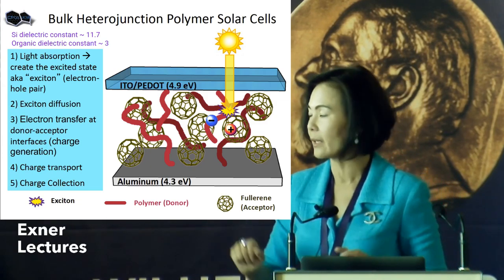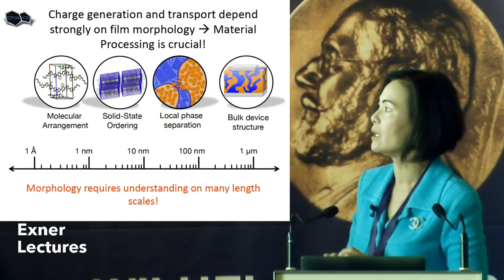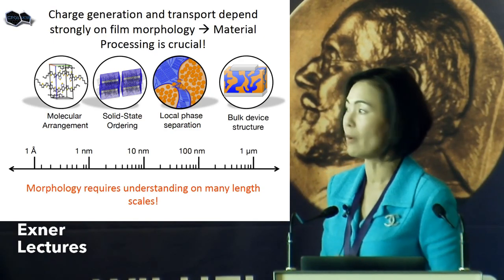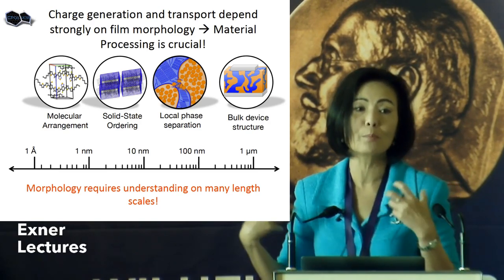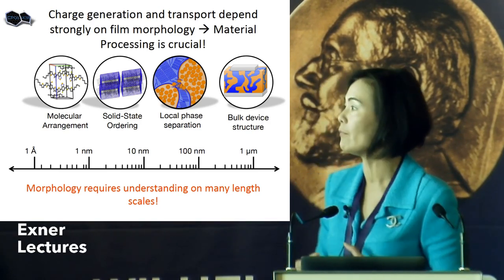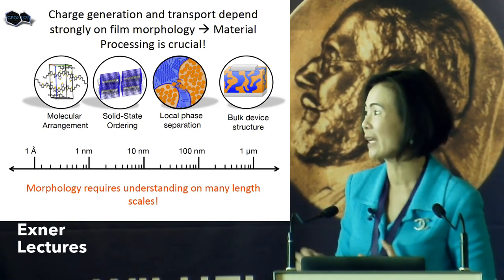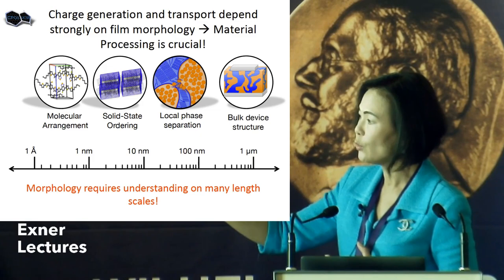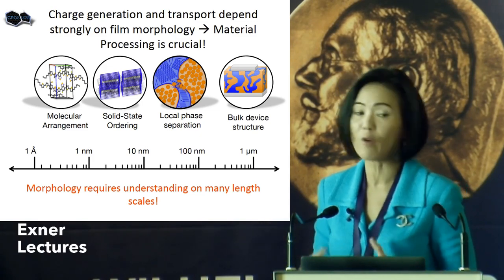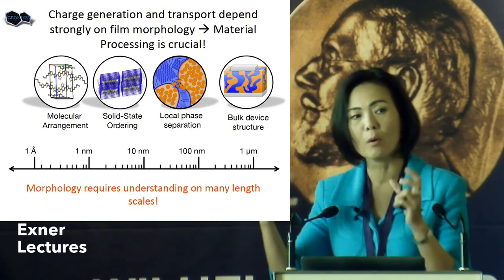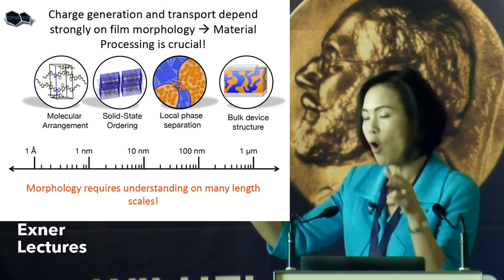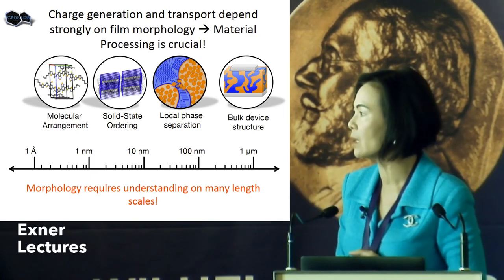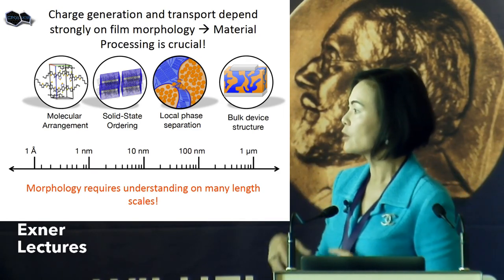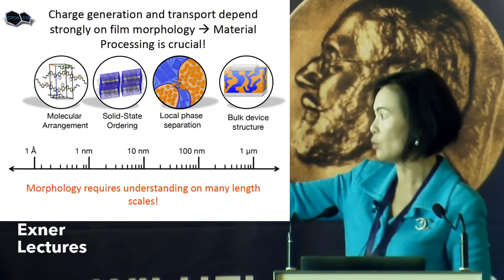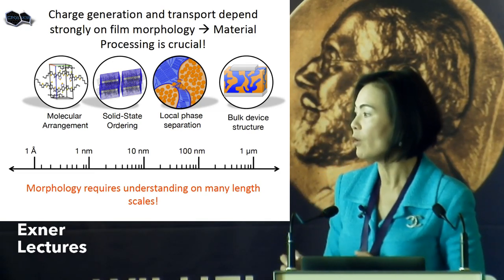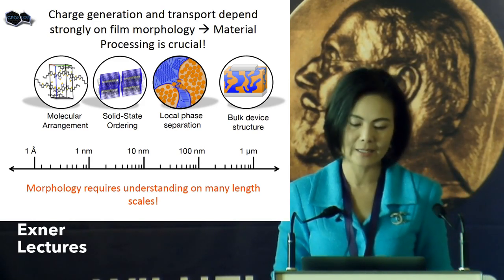And you can see in this cartoon demonstration that the charge generation and transport depend strongly on the film morphology. So controlling the film processing method so that you can control the film morphology is extremely important in the organic solar cell community. And I could show you here what is meant by morphology. Morphology means the molecular arrangement of the molecules, the order of the donor and the acceptor, because you blend two components together, so they phase separate, and then you also go to the bulk device structure. So therefore, morphology requires understanding on many length scales.